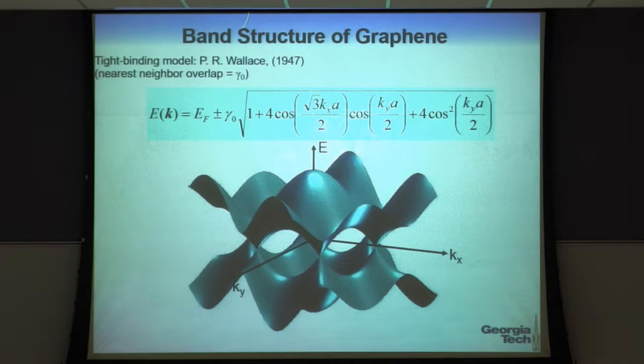So graphene, you might see, was discovered in 1947 by Phil Wallace. Well, okay, he did calculations based on a single sheet of carbon atoms, and he came up with an energy structure. This is a two-dimensional energy versus momentum. Well, it's crystal momentum. If you multiply by h bar, you get essentially a momentum. So this is energy as a function of momentum in kx and ky directions. And what you find are these interesting regions where you get two cones intersecting at a point. That point is known as the Dirac point.